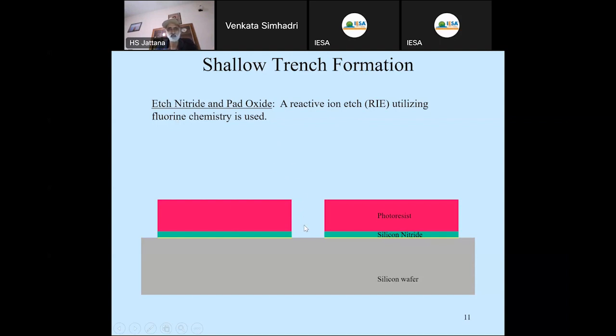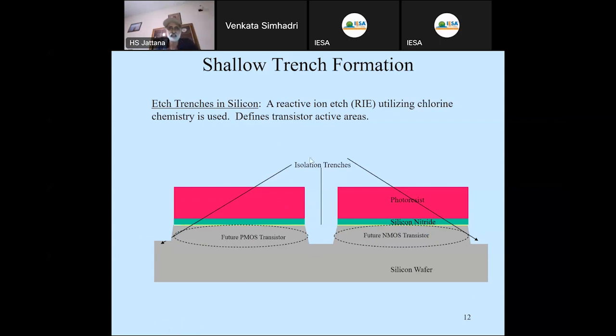So here I am using a fluorine chemistry to remove the oxide and nitride, and fluorine chemistry is used in reactive ion etching. And from here also, it's basically a cross section of the wafer. So here this is done, and finally now I have to etch the silicon to some extent, and like this, make a trench in the silicon wafer, and for that I will use a chlorine chemistry for doing this etching. This also is, you can say, dry etching, reactive ion etching.